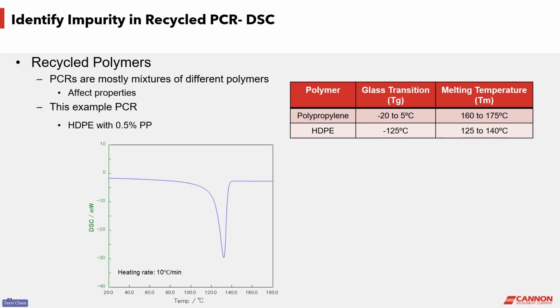The DSC technique is also commonly used in polymer recycling for the purpose of identifying and quantifying impurities. So in this case study, from a DSC temperature scan, we observed a big crystal melting at a temperature around 130 degrees C, which correlates to the melting of HDPE. From these results, we can say that this particular batch of PCR resin mostly contains HDPE.